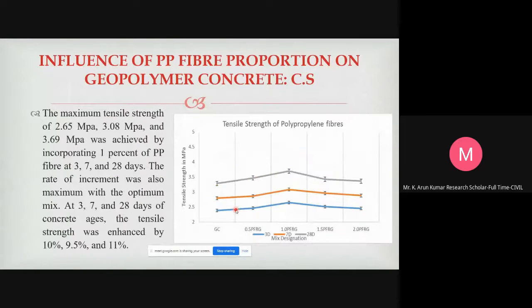The maximum compressive strengths of 24.49 MPa, 29.95 MPa and 42.9 MPa were achieved by the addition of 1% of PP fiber, where the strength increments were 61%, 47% and 22% compared to the control mix. The increment was due to the high degree of compressibility of PP fiber, and the findings correlate with previous studies.